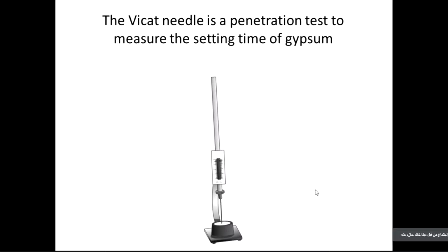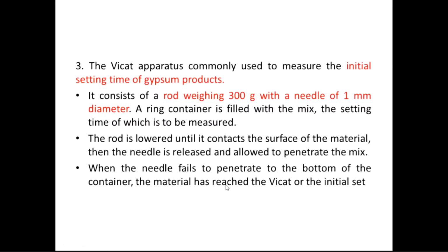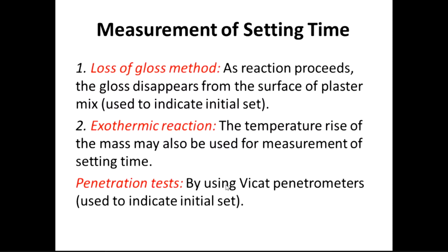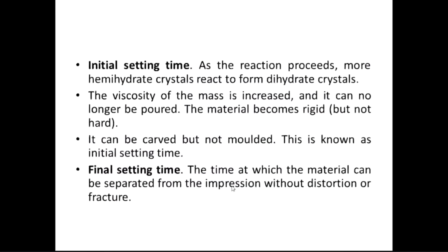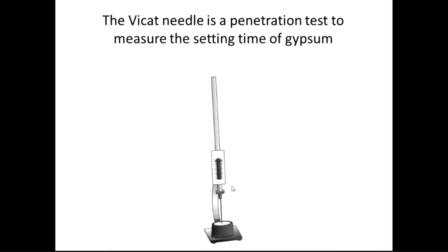Bring the impression or cast here and apply the pressure. If the instrument penetrates the cast, that means we have not reached the setting time. But if you apply this instrument and it does not penetrate the cast, it means you reach the final setting time.